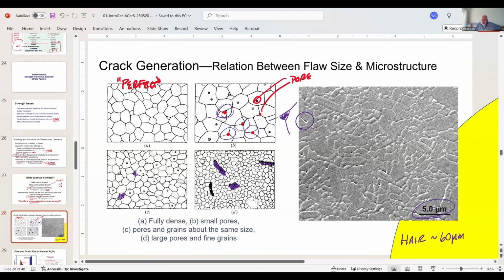And you can see this is a fine grained microstructure, but there are elongated grains. For example, here we have an elongated grain. And then I have equiaxed grains in here as well. I like those. But I have defects that show up in this microstructure. Now, these are really small defects. So if I were to test this microstructure, I would likely get a high strength.